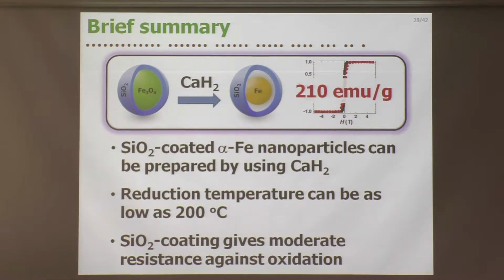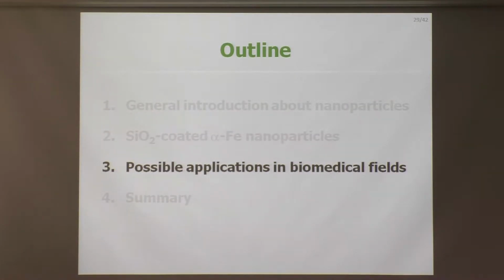Now let me briefly summarize this part. As I repeatedly said, we now have alpha iron nanoparticles coated with SiO2, and we confirmed reduction temperatures can be as low as 200 degrees Celsius. Our nanoparticles have moderate resistance against oxidation. Now that we have this kind of nanoparticle, what should we do? What we did was to find the application of our nanoparticles.